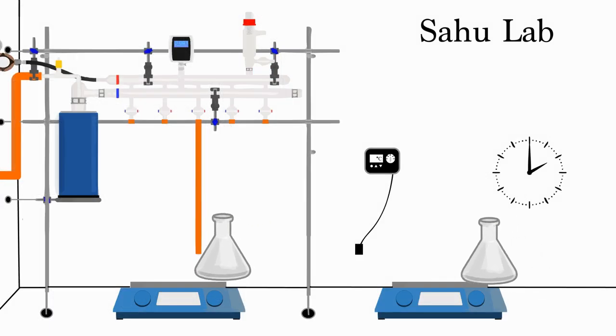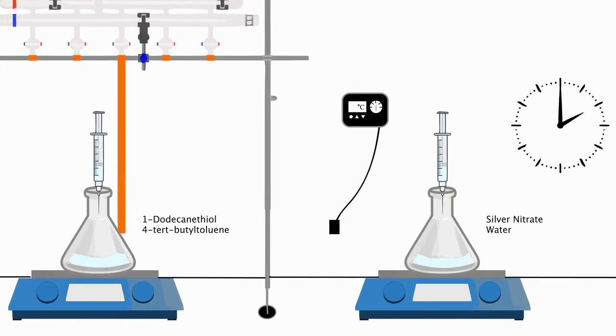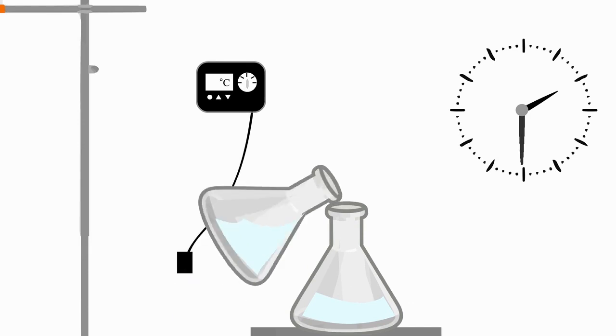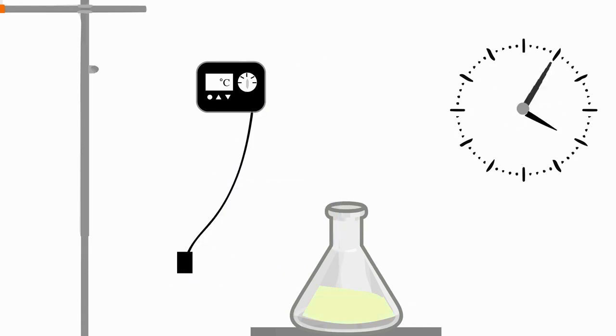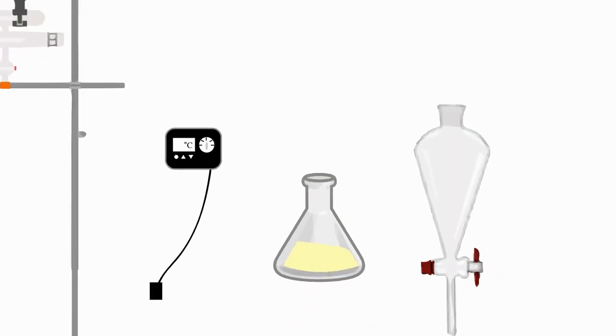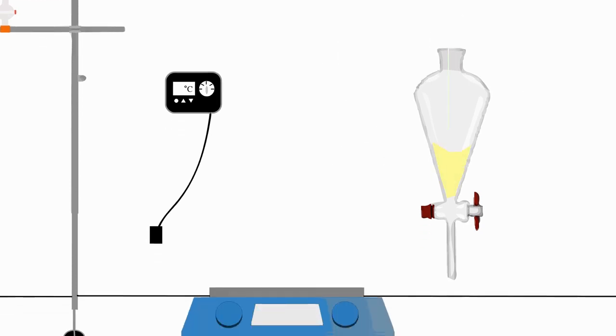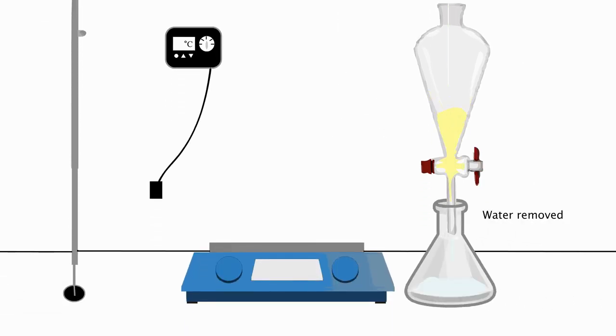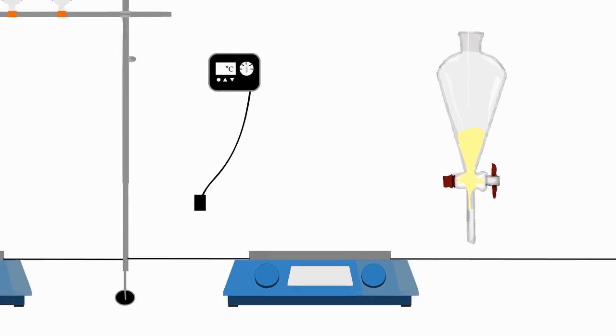Two solutions of silver nitrate and water and 4-tert-butyltoluene and 1-dodecanethiol are mixed and stirred overnight, forming a foamy yellowish silver precursor. The excess water is poured off with a separatory funnel into a beaker for disposal, and the precursor is put into a round-bottomed flask.